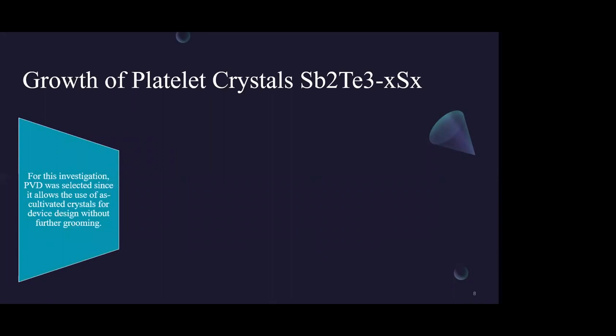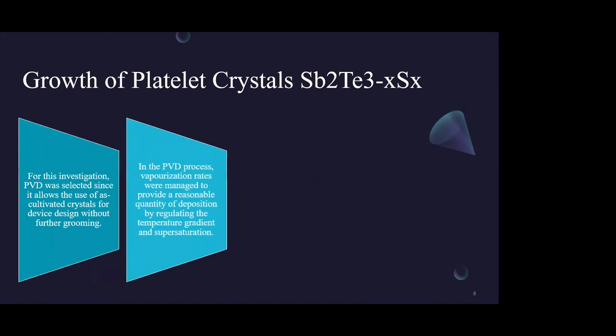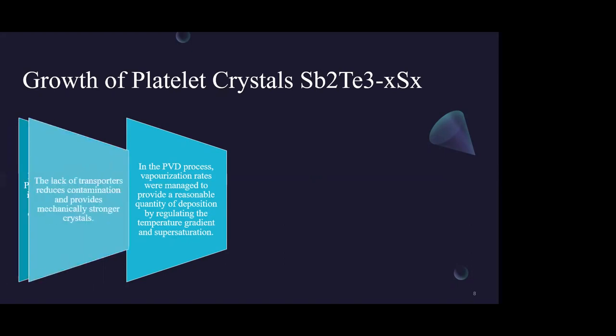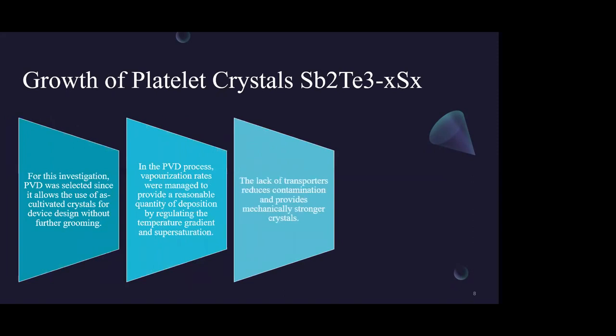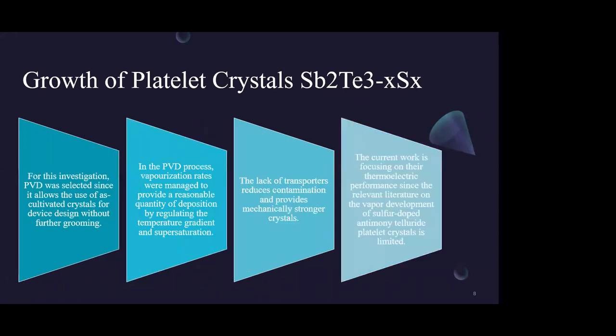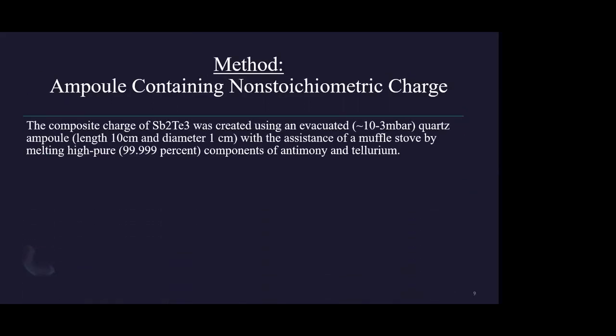For this investigation, PVD, that is physical vapor deposition, was selected since it allows the use of as-cultivated crystals for device design without further grooming. In the PVD process, vaporization rates were managed to provide a reasonable quantity of deposition by regulating the temperature gradient and supersaturation. The lack of a transport agent reduces contamination and provides mechanically stronger crystals. The current work focuses on their thermoelectric performance, since relevant literature on the vapor growth of sulfur-doped platelet crystals is limited. So this is the main work of my research.